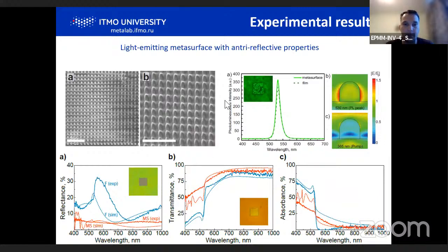And you see here that in reflection we have suppression of reflection from 30% down to even up to 5%. And this is because of improved transmittance of this array. And still, we have good photoluminescence. We have even enhanced photoluminescence from this square, meaning that by Mie resonances, we not only manipulate light, but the direction of scattering of light, but also we provide some enhancement of photoexcitation and emission of this layer.